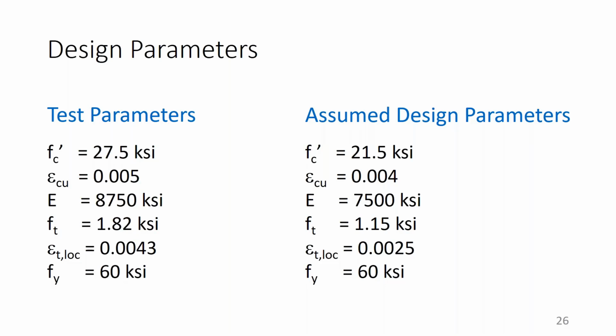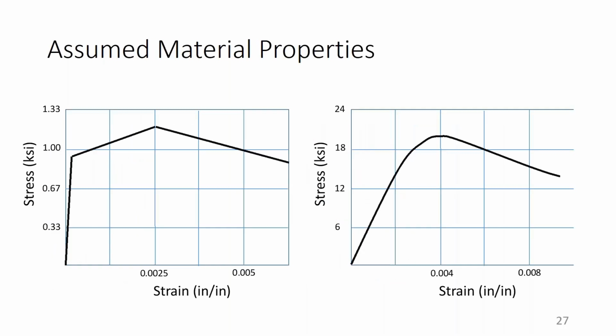And then we said we would check towards the end from the trucks, and I'm going to show this data shortly. So for example, the compressive strength that we got in the lab was 27 KSI. We assumed 21.5 KSI. Going all the way down, the localization strain was 0.43%, 0.0043. We assumed it to be 0.0025, which is the minimum allowed at the time by the Federal Highway guidelines. By the way, that was not yet approved, so we were kind of using it just for guidance. Also, the tensile strength of the material, which you cannot ignore because it's so high, was 1.82 in the tests. It's 1.15, okay, for the design.